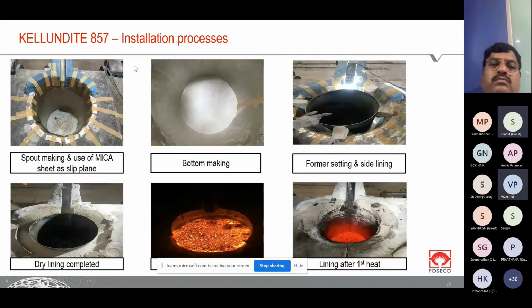So just what we have seen, before installation, the spout needs to be made with the blue ram. Then make use of mica sheets. Then we have to prepare the bottom with the help of a vibrator. If it is not there, then ensure manually it is getting compacted very nicely. And after putting the former, we have to fill the lining. The sintering cycle needs to be followed. So here we need to ensure that the former should not melt before metal reaches the top. If it melts earlier, then that will be fast sintering and may result in early erosion of the lining.